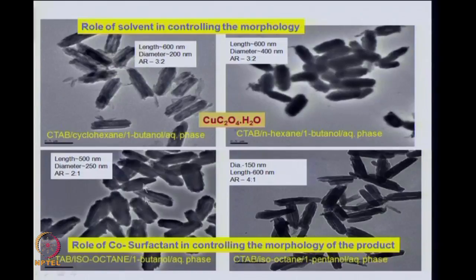Now, you can see the same thing, the solvent is controlling the morphology. So, you are changing from cyclohexane, that is the solvent here, to hexane, to isooctane, right. And in this case, we have changed from butanol, which is a co-surfactant, to pentanol, which is a bigger co-surfactant. So, the top two show you change in the dimensions of the nanostructured materials when you change the solvent. And the bottom two slides show you what happens to the morphology when you change the co-surfactant.